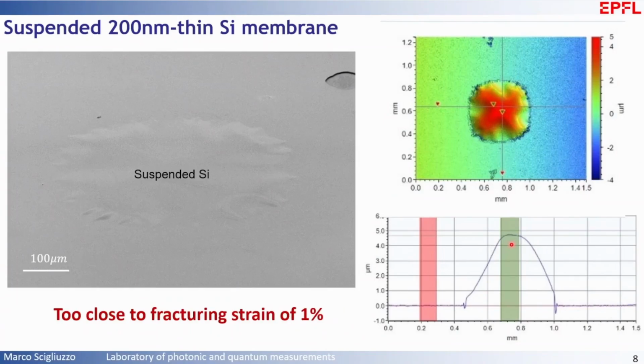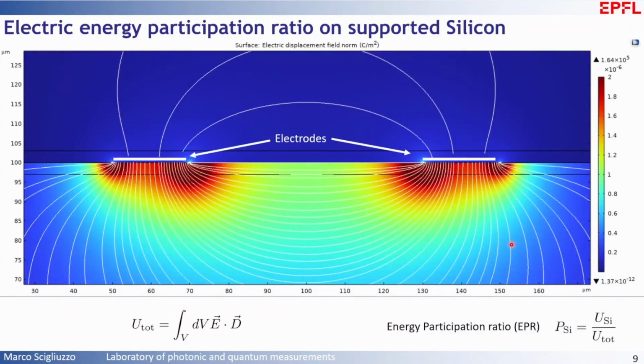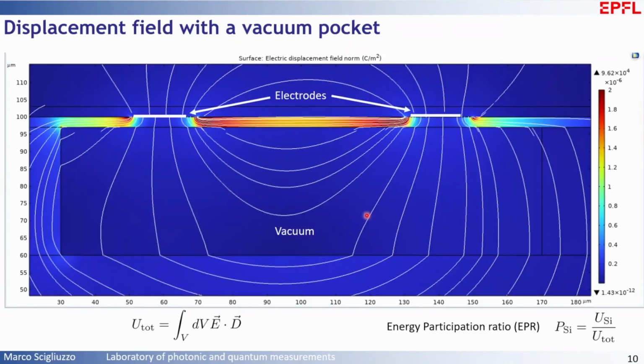Now we want to make a qubit on it, and as you know, when you make a standard qubit on a fully supported structure, you will have the dielectric constant of your silicon that will help in making relatively large capacitance. We shoot for 100 femtofarad more or less. But now if you have a suspended element, either you make a very dense capacitor with an interdigitated capacitor, or you need a very large area.